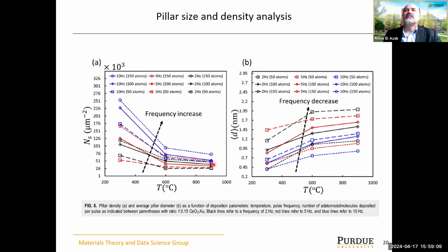The most important thing to observe here is the following. The density increases with frequency increase and with lowering the temperature. And the pillar size behaves the opposite way. Density means the number of islands that form in the beginning, they become many or they become a lot. The number becomes higher if the temperature is low and the rep rate or the deposition rate is high. The reason for this is that at lower temperature, atoms don't get a chance to diffuse much, and every small number of atoms in a small neighborhood will just aggregate, and you have a lot of these patches on the surface itself. As a result, you get thin pillars of larger density, and of course, the size behaves the opposite way of the density because you have fixed material in there.